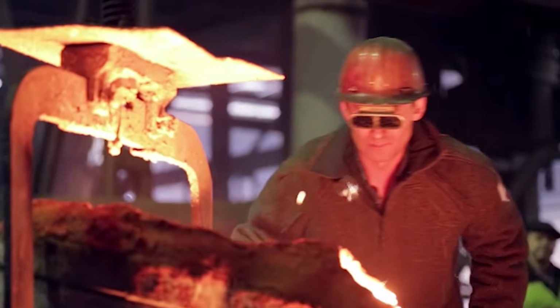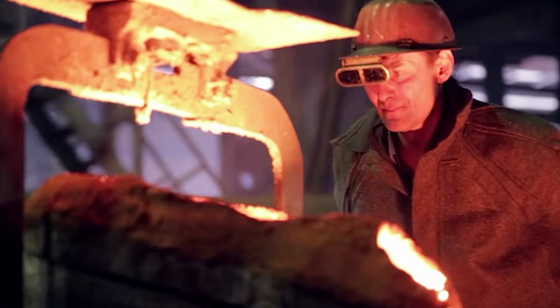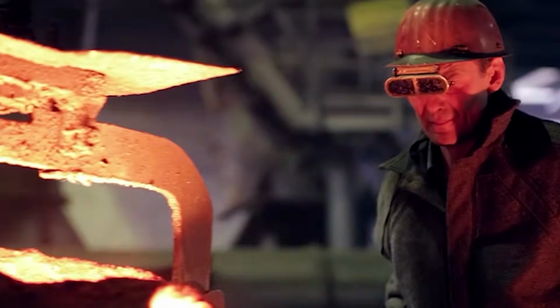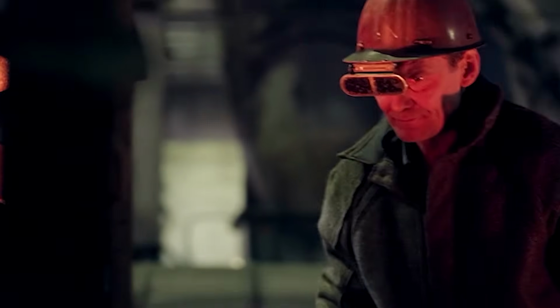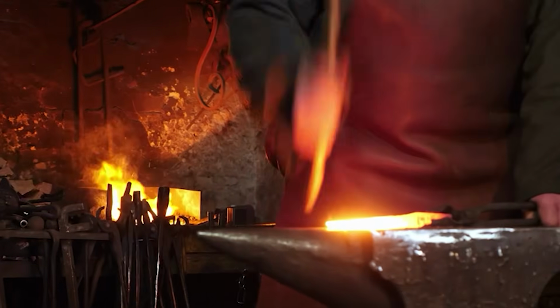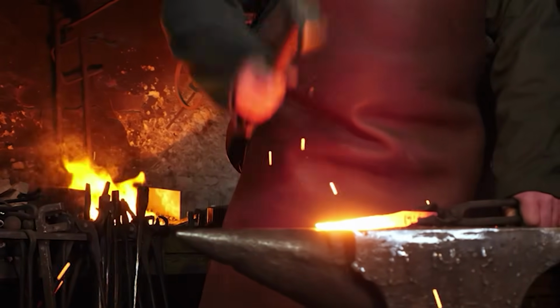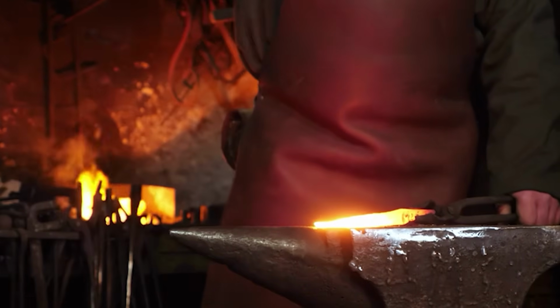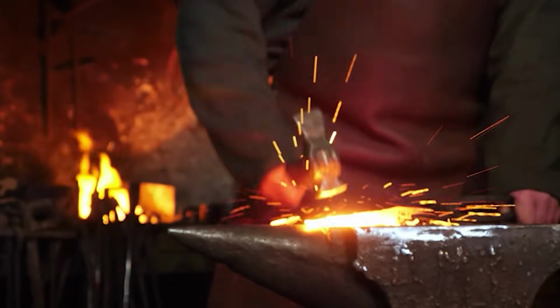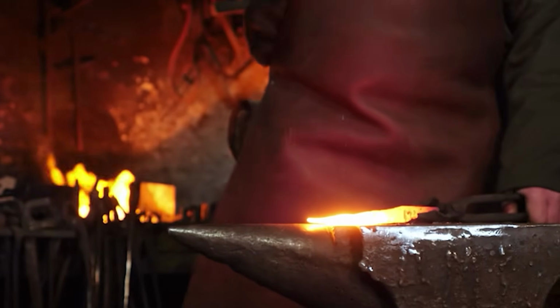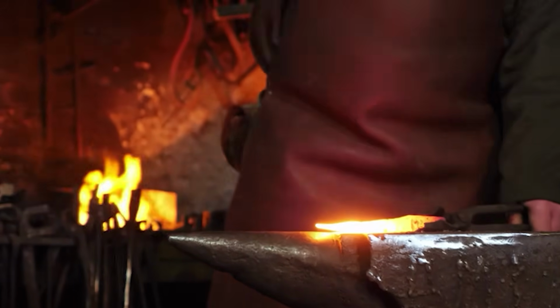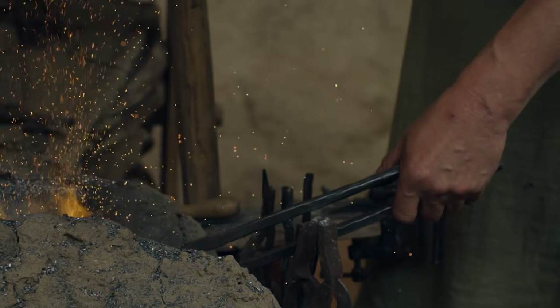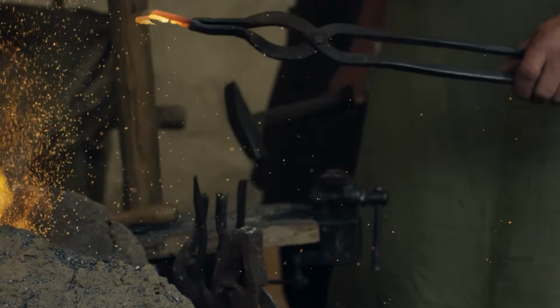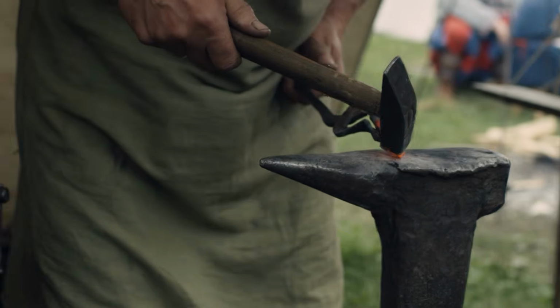Modern steel is cold-rolled. Bars of steel are pressed through rollers at room temperature, shaping them quickly and efficiently. Medieval smiths did not have that option. They had to work their iron hot. The bloom was reheated in the forge and hammered over and over. This hot working did something crucial. It drove out some of the slag, yes, but it also compressed and aligned the slag that remained, stretching it into those microscopic fibre networks.